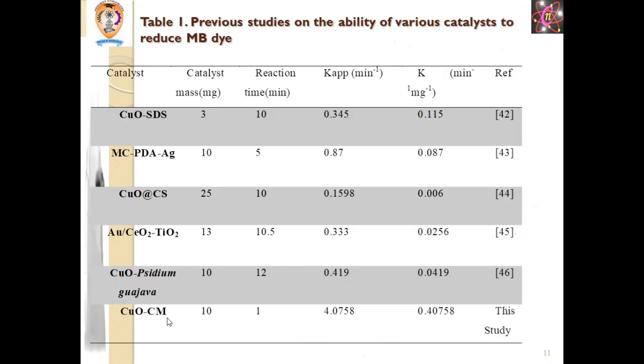The results were summarized in this table, and as you can see, our results are highly improved compared to the previous literature. That's the reason we said we were successfully synthesizing this effective catalyst for the catalytic degradation of organic wastes from industrial effluents.